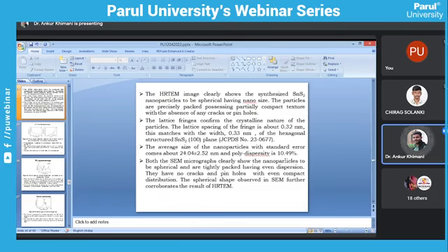The average size of the nanoparticle with standard error comes out 24.04 nanometer, and the polydispersity, that is the variation in size, is 10.49%. Both micrographs clearly show the nanoparticles to be spherical, tightly packed, having even distribution, and they have no cracks and pinholes with even compact distribution. And the spherical shape observed in SEM further corroborates the result in HRTEM.